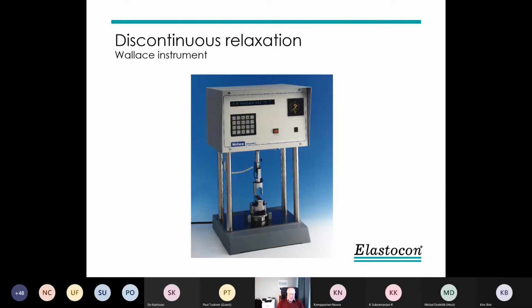The instrument at that time was developed by Wallace in England and was measuring in the test fixture. You see one in the picture here, where a load cell was fitted to a pneumatic cylinder, more or less, and compressed the sample inside the test rig a little, so it didn't have any connection with the spacers anymore. According to that method, it's allowed to do a little extra compression to have the sample getting free of the spacers, so the counterforce can be measured. But it is very tricky to get repeatable results. That test rig is then put into an oven to make the aging at an elevated temperature and taken out at suitable intervals. Quite a lot of manual work, and quite a lot of errors can be introduced.